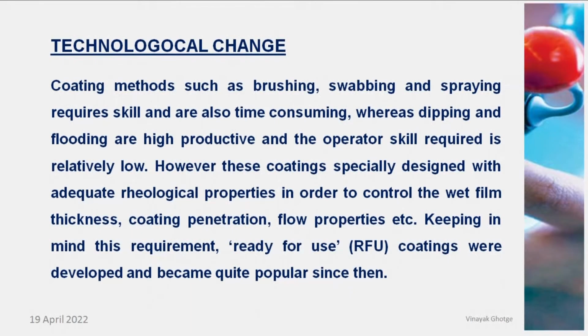The coating methods such as brushing, swabbing or spraying definitely require skilled operators and are also time consuming as far as productivity is concerned. Whereas processes like dipping and flooding are highly productive and the operator skill required is relatively low. However, such coatings are specially designed with adequate rheological properties in order to control the wet film thickness, coating penetration, flow properties, etc. And keeping in mind these requirements, ready-for-use coatings were developed. That means coatings in ready-for-use or paste form. And then these coatings became very popular.